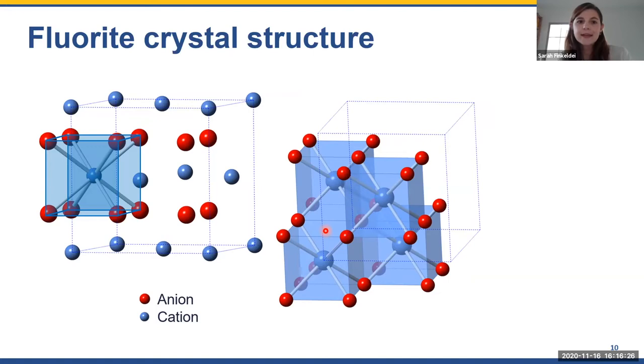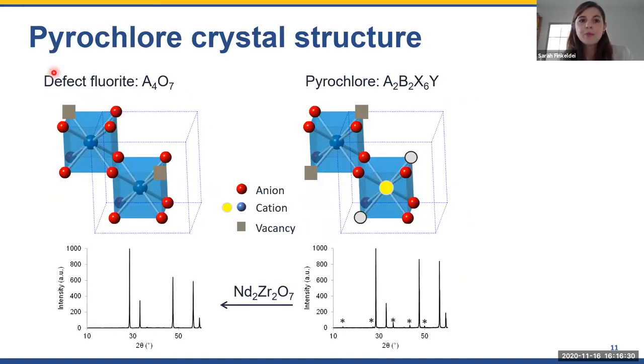So if we go ahead and introduce some disorder into the system now by removing 1/8 of the oxygens, what's going to happen is we will create these, depicted as gray cubes, oxygen vacancies in our material. And if those are randomly distributed in the structure, we are talking about a so-called defect fluorite structure.